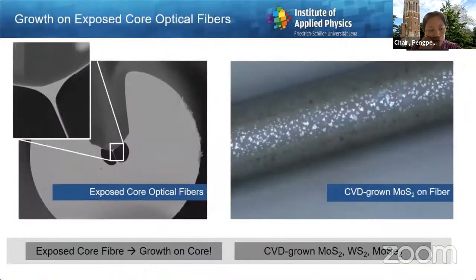We took a special kind of optical fiber, which you can see on the left-hand side here, in cross section. So you have the fiber extending out of the screen. The gray area is silicon dioxide, so it's glass, and all the dark areas are air. Now the photonically interesting part happens in the center of this fiber, where you have a guiding core, which is made of silicon dioxide, the optical mode propagates in this core, and it's surrounded by air.